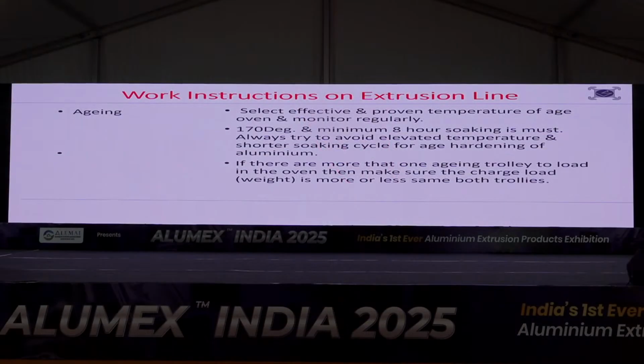Then aging, we have already discussed. Most of the people go for elevated temperature and short cycle. It will not save you money. Surely, almost 80% or 50% of aging will require a re-aging process. And after re-aging, we get surprised either the hardness has gone down or it is not achieving further. Do not do it. Follow this. It will give you better result and it will save your reprocessing time.